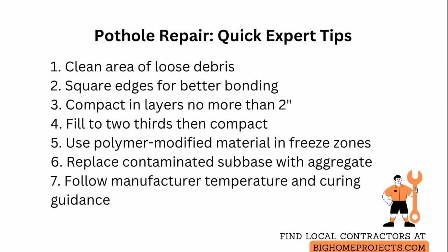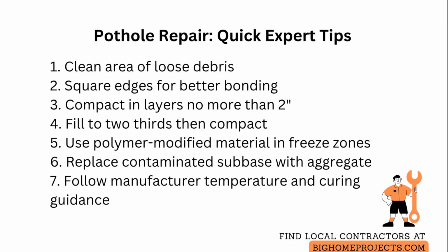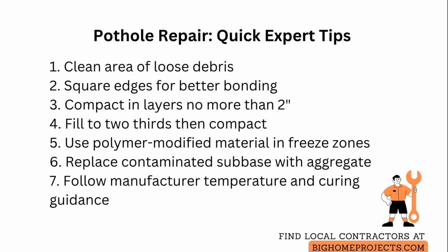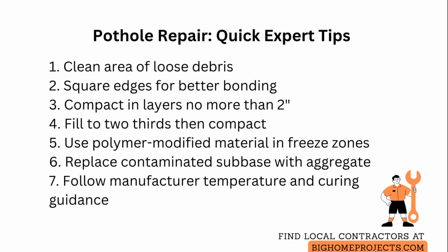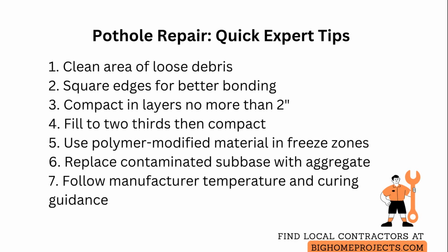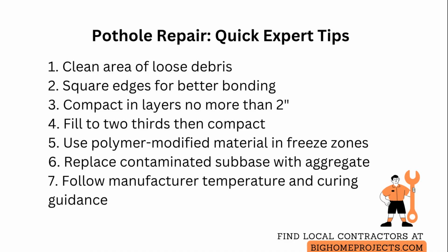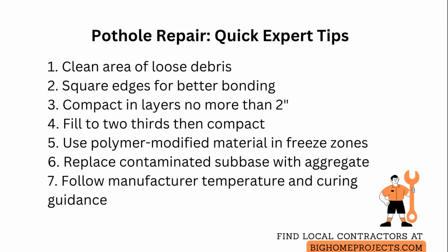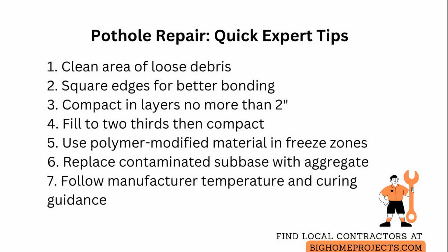When addressing freeze and thaw regions, select a material with polymer modification and ensure base stabilization by removing contaminated subbase and replacing with crushed aggregate if it moves under load. For temporary emergency fixes in low traffic areas, a well-compacted cold patch can last months, but plan permanent repairs with proper edge cutting, tack coat, and an asphalt overlay when possible. Always follow manufacturer temperature and curing guidance and wear protective gloves and eye protection.